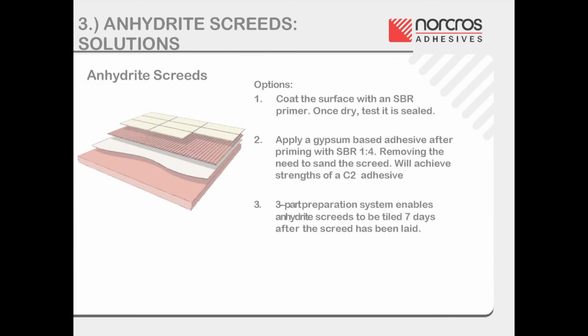Once both coats are dry, check that the screed is completely sealed by dropping water onto it. If the water sits on the surface in a bubble, then it is assumed that the screed is sealed. However, if it is absorbed, then add a final coat mixed at 1 to 2 parts SBR to water and allow to dry.